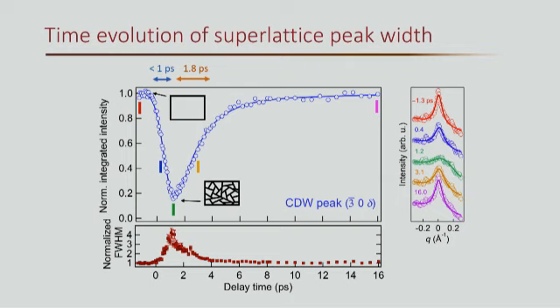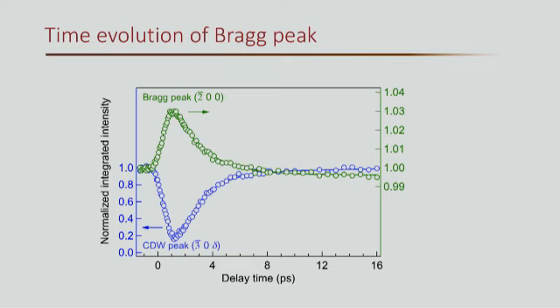So of course, as an experimentalist, you are thinking, can we actually suppress it fully? Yes, we can, by just tuning up the laser power to pump it. If you're really hardcore about destroying the CDW peak, you can also burn the sample. So this is what we did exactly.